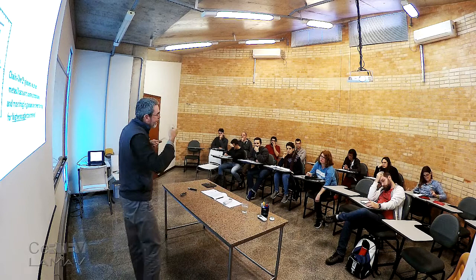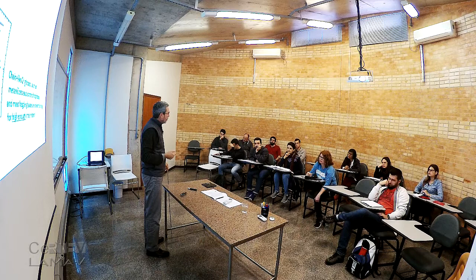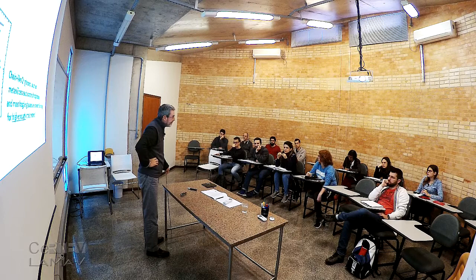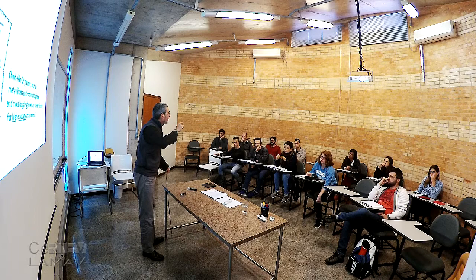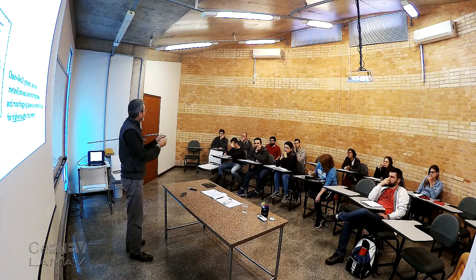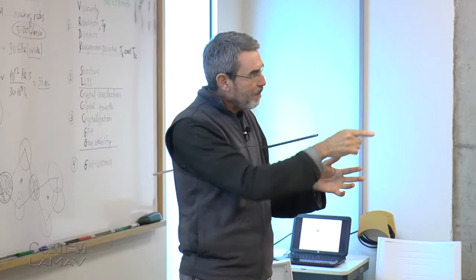So what type of glassy material can be shear thickening? Pure silica. Why? Because it has a very high viscosity. Yeah, very high, but pure silica is Newtonian because the structure does not change with shear. Glass ceramics can be shear thickening. If you have a glass with crystals, like plate-like crystals, maybe your material is shear thickening. We have to test this at some stage.